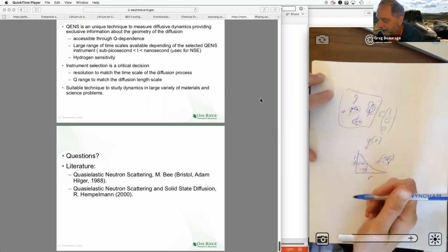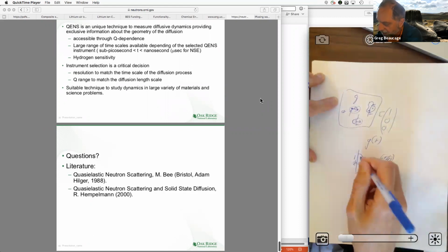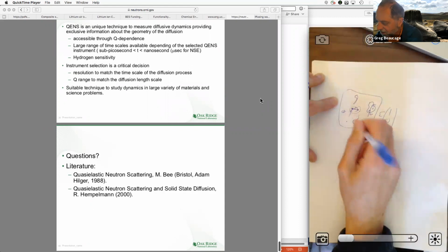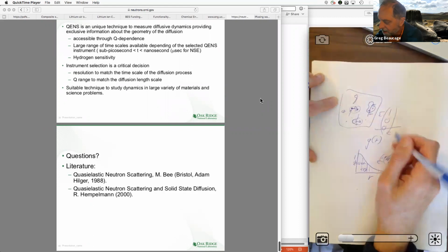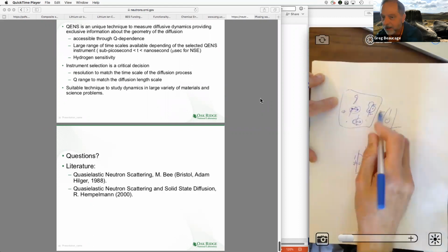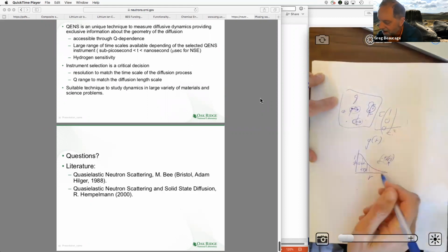Right? So these are all different. You throw in a rod with zero length, which is a dot, then you just get the concentration. So you normalize this kind of sum by the concentration squared, because it's two points. That's how you normalize it, by the concentration squared. And then it's going to be this decay function, you get that length, right?